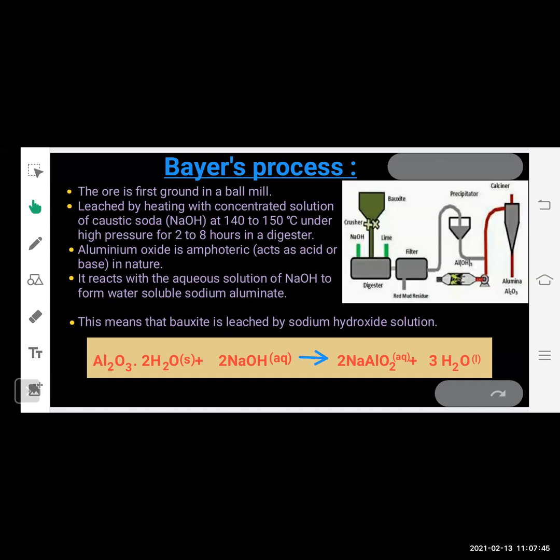hours. And as a result, aluminium oxide, which is amphoteric in nature, amphoteric, that means it is acting as acid as well as base, reacts with the aqueous solution of NaOH to form water soluble sodium aluminate. You can see the reaction here. This is the bauxite ore. It reacts with sodium hydroxide in the digester, and it forms sodium aluminate along with water. So this means that bauxite is leached by sodium hydroxide solution, and we get sodium aluminate.